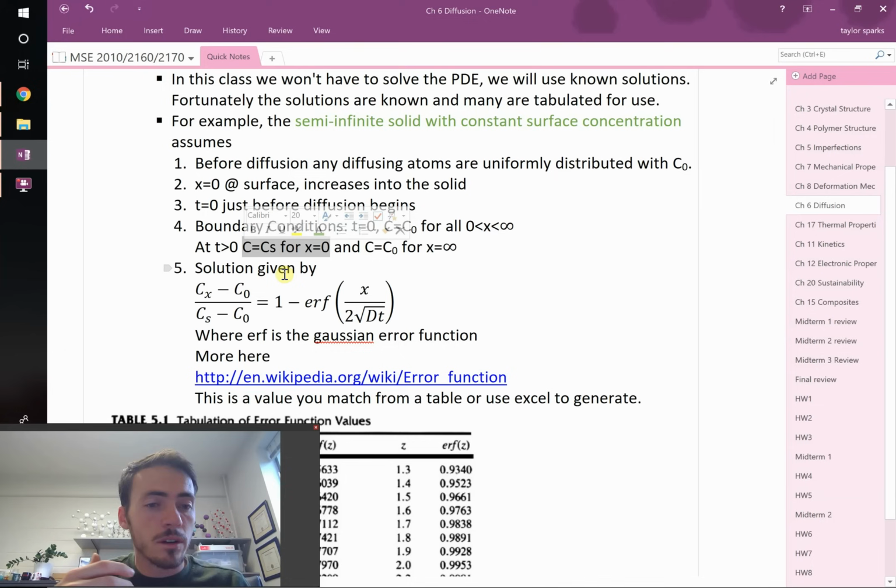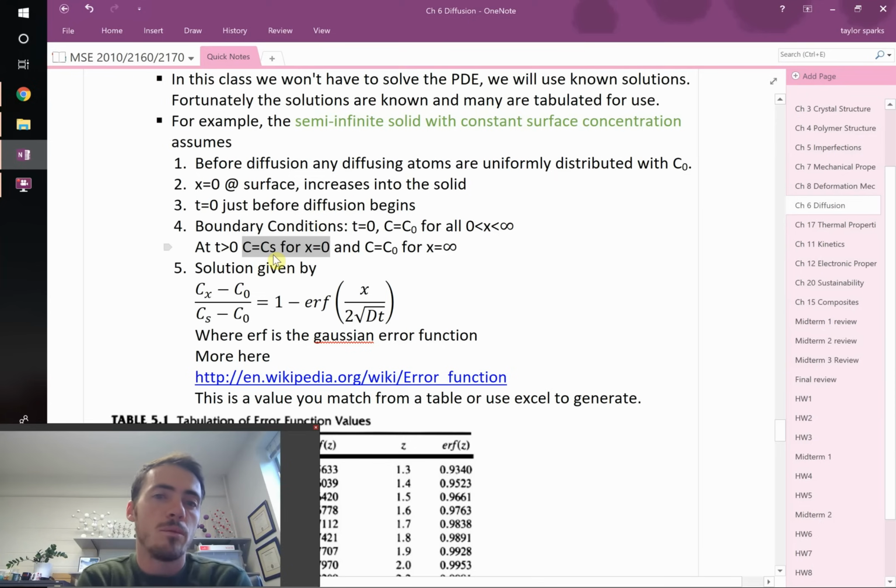In the semiconductor industry, we're going to do a problem in a minute on it. They'll sometimes put a finite amount of, say, phosphorus atoms on silicon, and then they'll let that diffuse in. But they're not adding more phosphorus and keeping it fixed at the surface. They're letting it diffuse in, so that surface concentration would go down in that case. For this solution that we're showing you today, that can't be the case. The surface has to stay. So it basically means that you're constantly supplying new material to the surface to keep that concentration at CS.